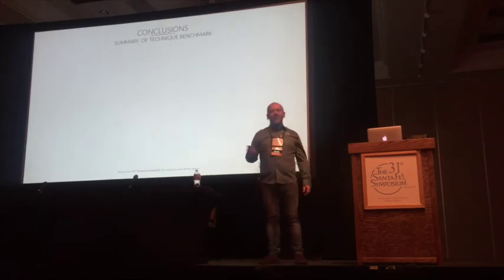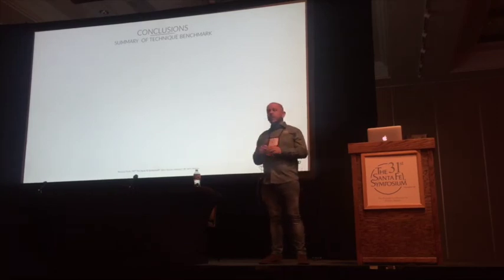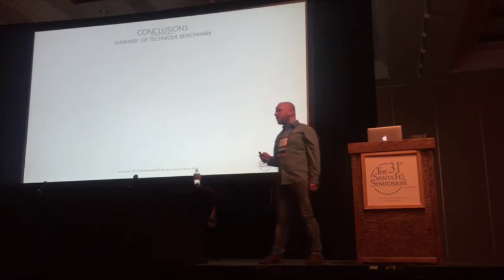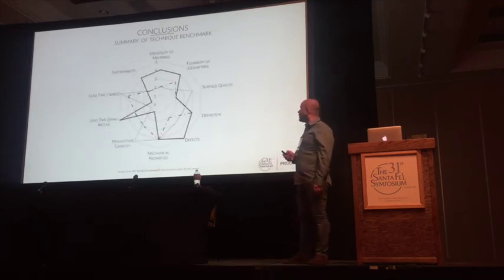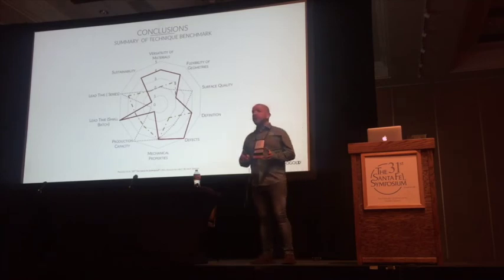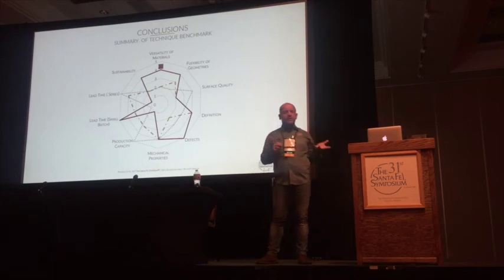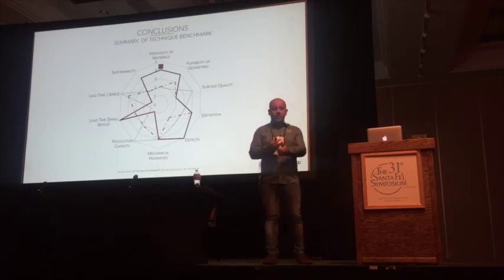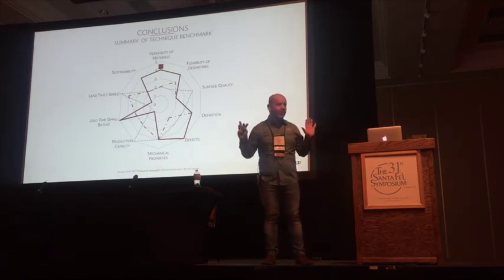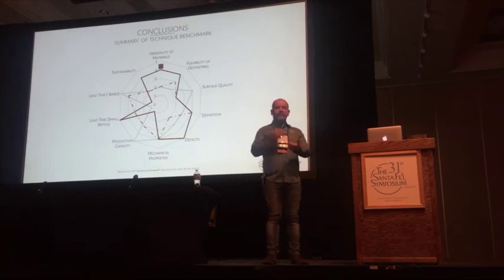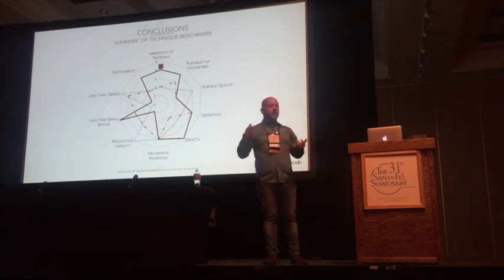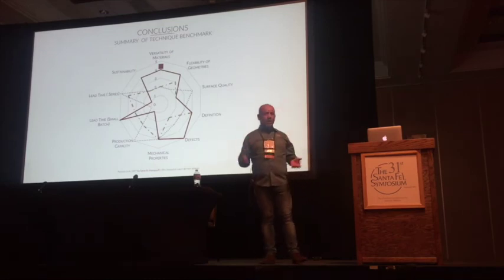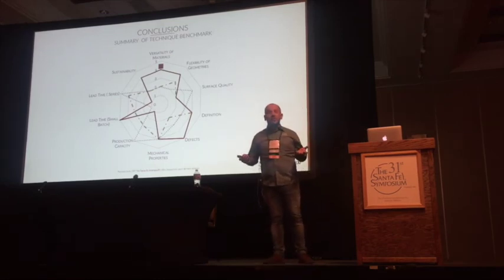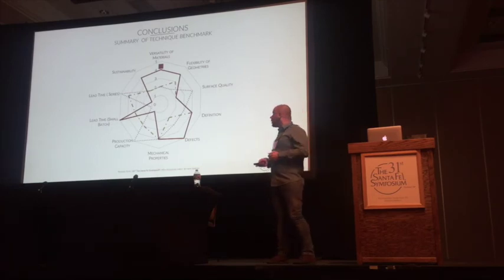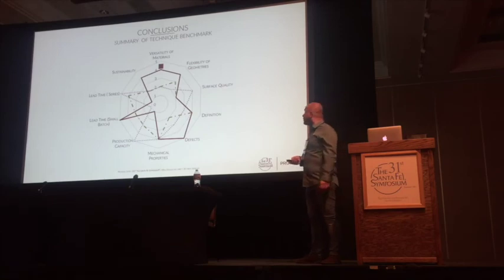So we were doing something like giving marks for every single characteristic that we were benchmarking. And you see here our radar. We start from versatility of materials. Of course, here the winner, the technology that is much more versatile is 3D metal printing, since you can print in the same printer, of course, if you clean. So you have to print, as I said before, titanium, gold alloy, platinum alloy, steel, or cobalt, chrome, whatever is the metal that you like, you can. Except, I think silver is not something very sexy for 3D metal printing. Or copper alloy is quite tough.